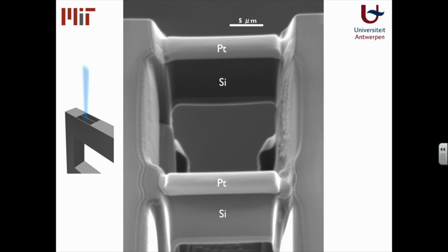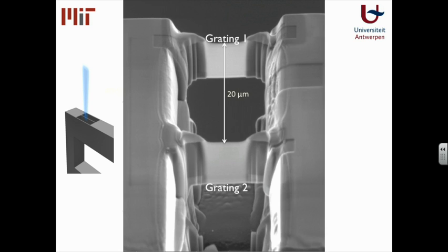The last step is to reduce the energy from 30 kilovolts to about 2 to 5 kilovolts, and also reduce the current to polish these gratings down to a thickness of about 40 to 50 nanometers or so. And finally, we get two thin crystalline gratings separated by, in this experiment, about 20 microns. Again, because they're derived from one chunk of single crystalline silicon, they are automatically aligned with one another. And also, because they're all on a TEM grid, we can directly take this interferometer and insert that into any old TEM. In our experiments, we use a JEOL 2010F.